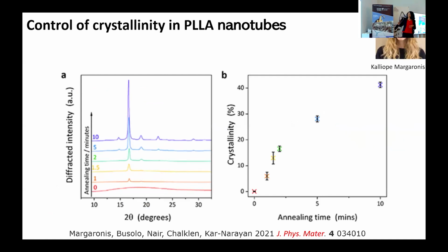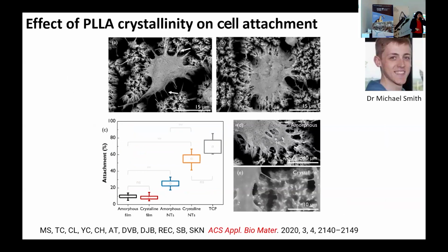My student Callie did quite a bit of work on how to control the crystallinity. So in her case, she was controlling the crystallinity of these nanotubes as a function of the annealing time, as you can see. So she did a lot of X-ray work and worked out what the ideal conditions were to get highly crystalline nanotubes. So again, starting material is the same. You can go from almost amorphous to in this case 40% crystalline.